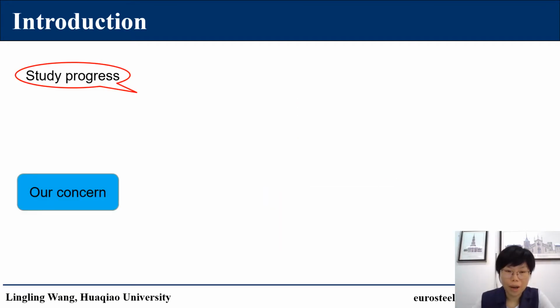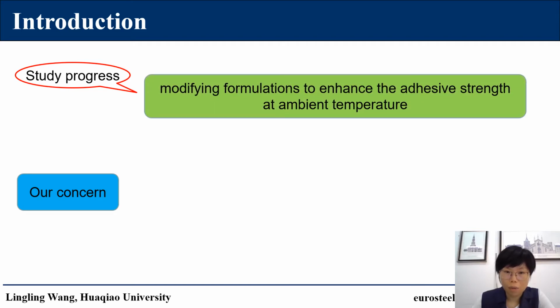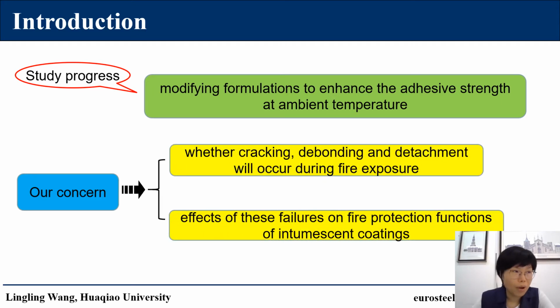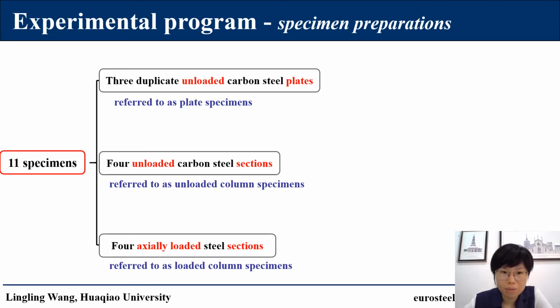A few studies have been carried out on the bonding properties of intumescent coatings. However, these studies have focused on modifying formulations to enhance the adhesive strength at ambient temperature. Engineers need to evaluate whether cracking, debonding, and detachment will occur during fire exposure and the effects of this failure on fire protection functions. To investigate this problem, 11 specimens were tested according to the mechanical loading conditions and substrate geometry. That is, 3 unloaded plate specimens, 4 unloaded column specimens, and 4 loaded column specimens.